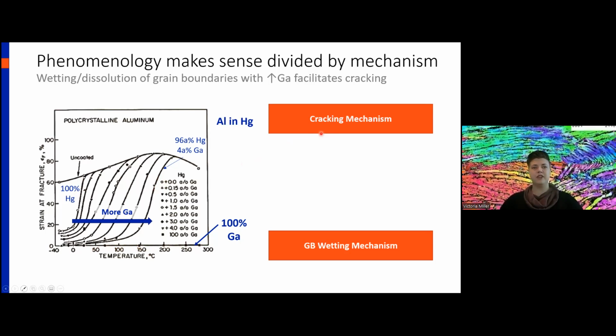This is a transition from an interfacial cracking mechanism to a grain boundary wetting mechanism. Gallium fully wets the grain boundaries. And as gallium starts to wet the grain boundaries, you get this wedge that acts as a pre-crack, so you get more severe embrittlement. Whereas pure gallium is full grain boundary wetting, which is why you get very little temperature sensitivity and complete embrittlement.